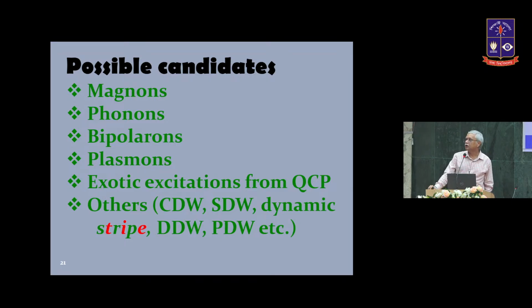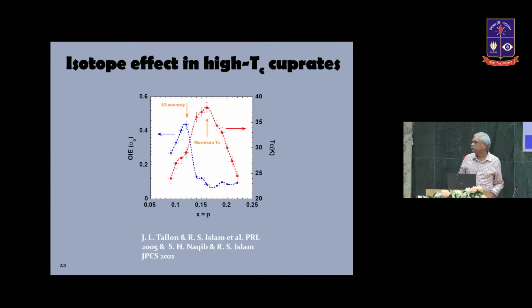There are other orders like the charge density wave, spin density wave. Dynamic stripe phase is a very prominent candidate. There is d-density wave, paired density wave, etc. So there are dozens and dozens of theoretical formalisms, but non-conclusive, which can really tell you exactly about the bosons that are at play. What we have done, we have measured the oxygen isotope effect, and you can see it here.